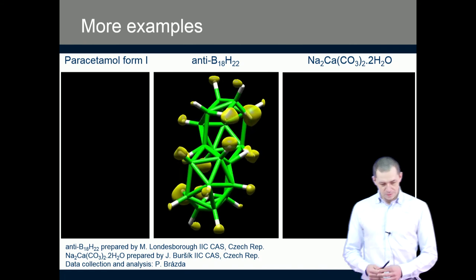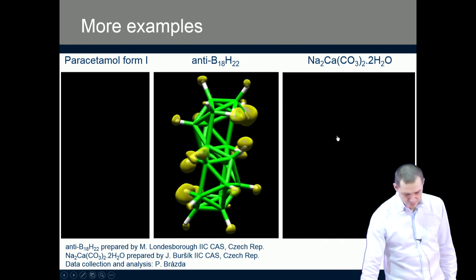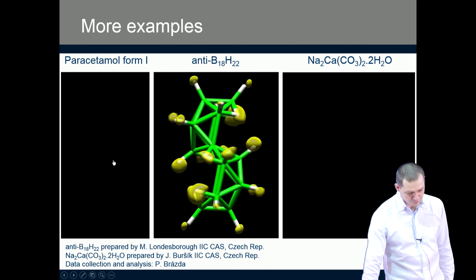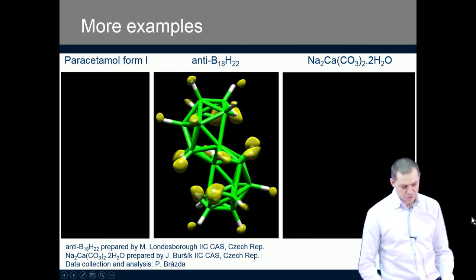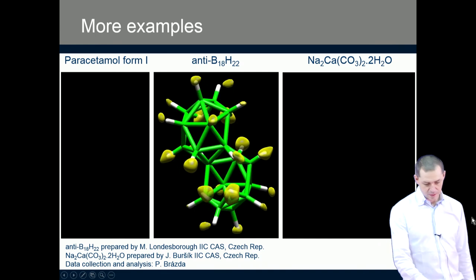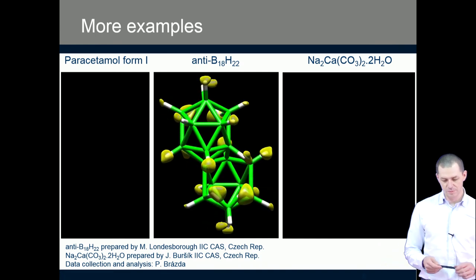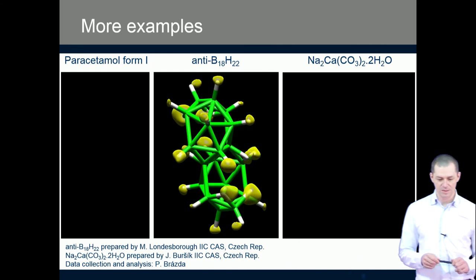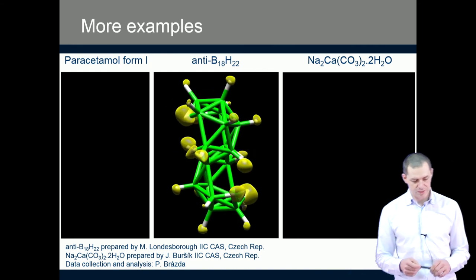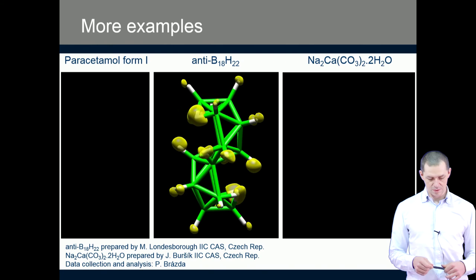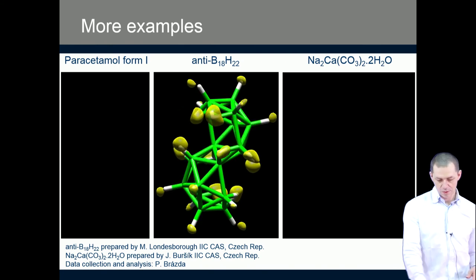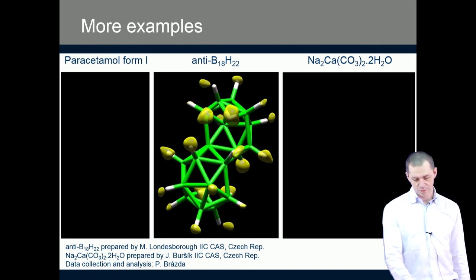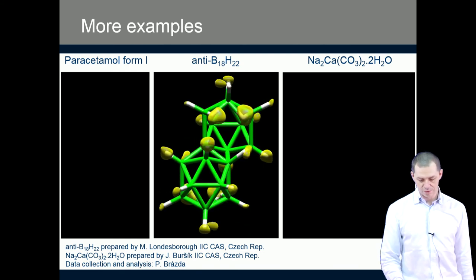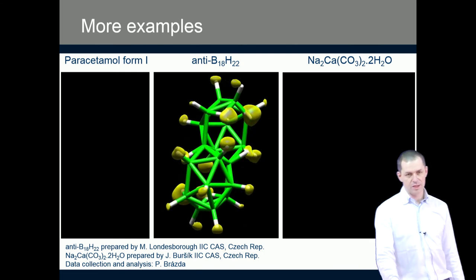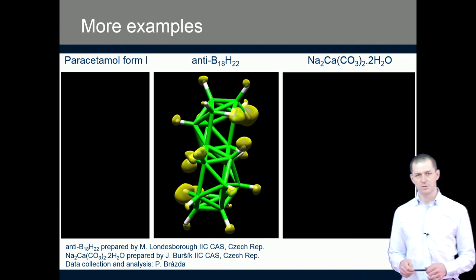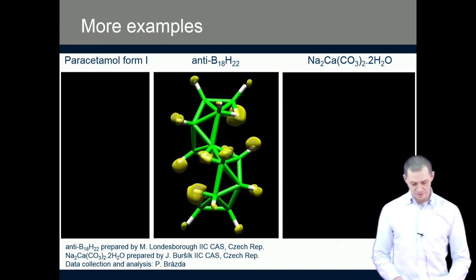A few more examples. Unfortunately, these videos just resist loading, so you can see just one of them. This is a boron cage with hydrogen atoms on that. Again, we can nicely see that the hydrogen positions are well located in the whole molecule. And these two, this would be another form of paracetamol. This is an inorganic structure, sodium calcium carbonate, where again the water molecules can be nicely found.